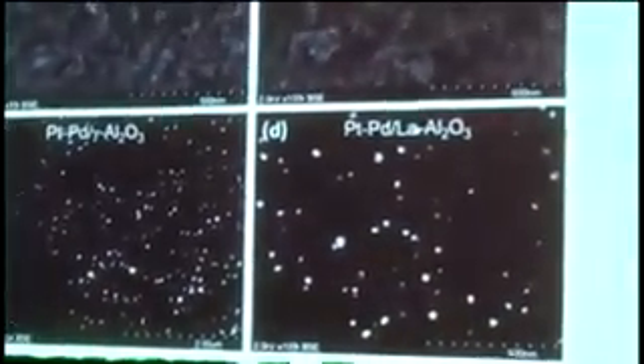So, it turns out that particles grow so large, you can use SEM. So these are SEM images of palladium on the 2 aluminas and platinum palladium. And these are at different magnifications. But as we're just looking at the pictures, you see clearly that the palladium is quite well dispersed. But the moment you have both platinum and palladium, you see large particles. And this is the normal alumina that we use in the automotive industry for wash coating.